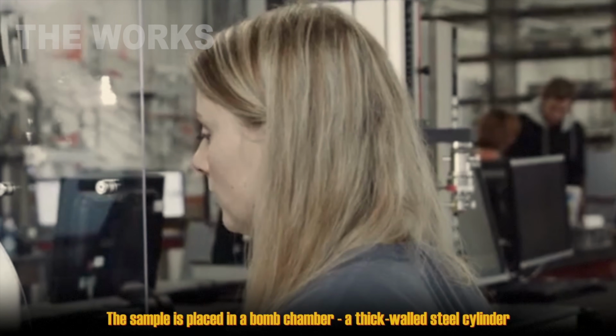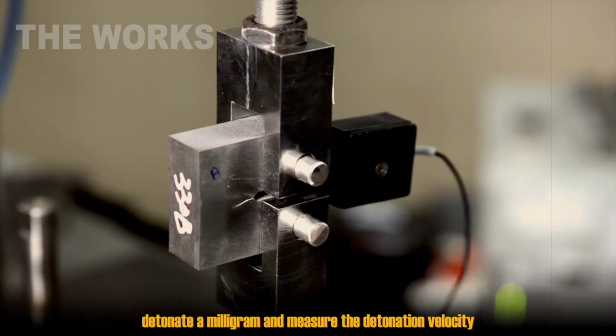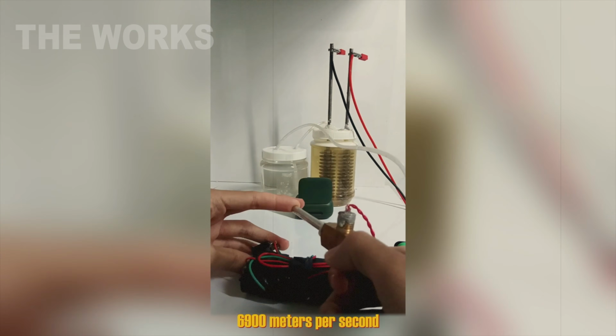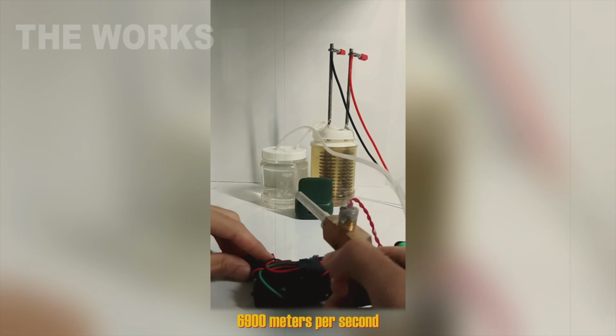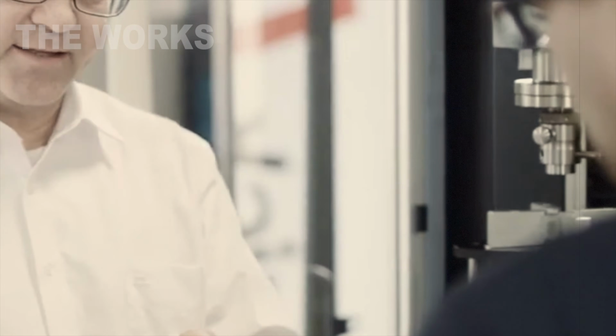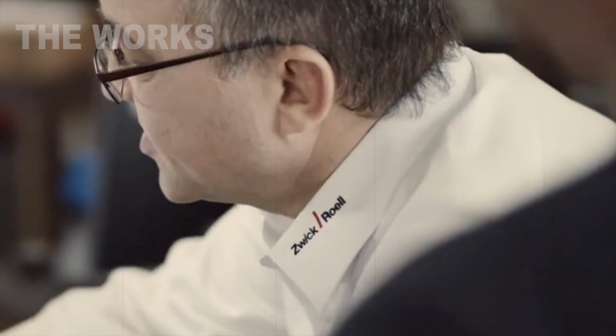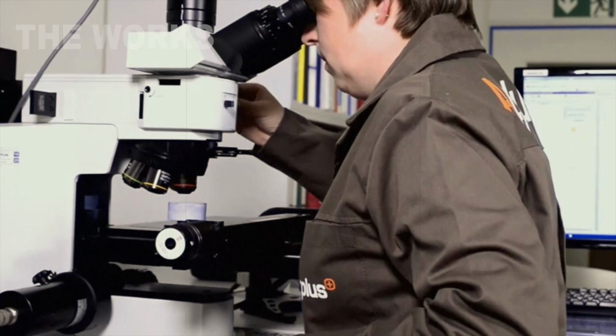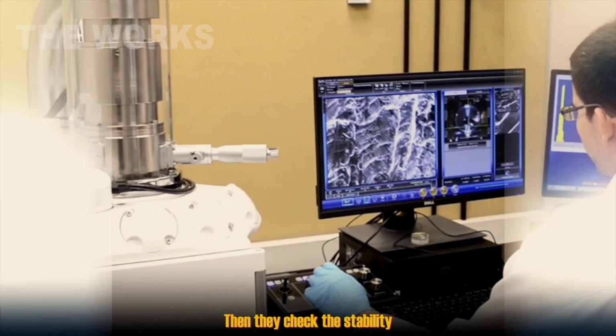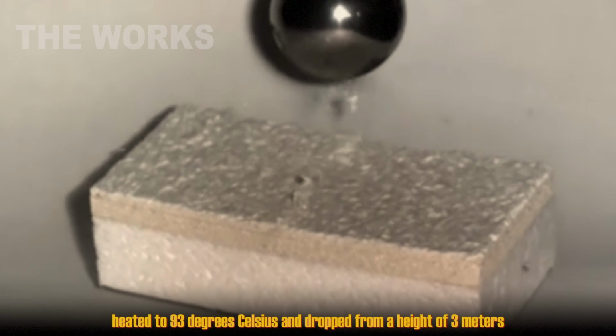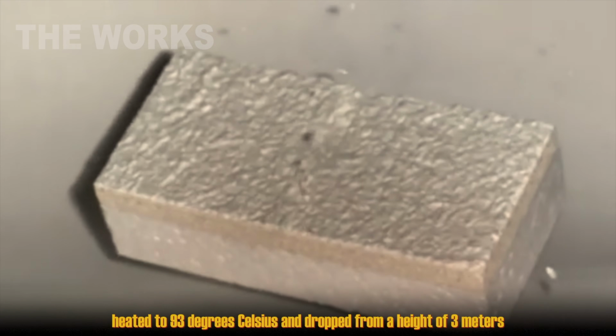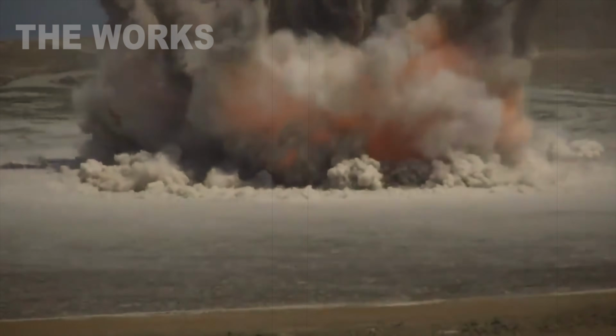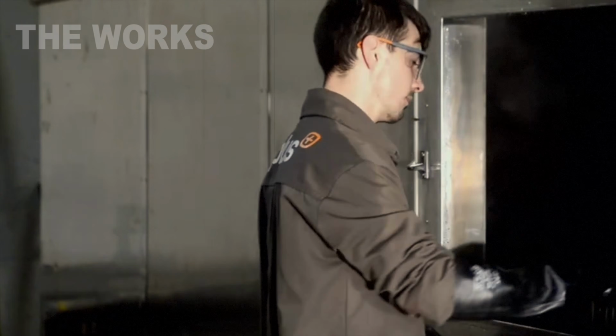This is where they test every batch. A sample gets placed in a bomb chamber, a thick-walled steel cylinder. They detonate a milligram and measure the detonation velocity, around 22,600 feet per second. If the velocity is below spec, that means there are impurities in the batch, or the crystal structure is compromised. Then they check stability. Heat it to 200 degrees Fahrenheit, drop it from 10 feet, it shouldn't crack or detonate.